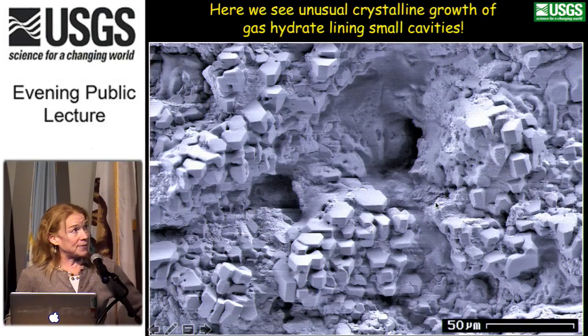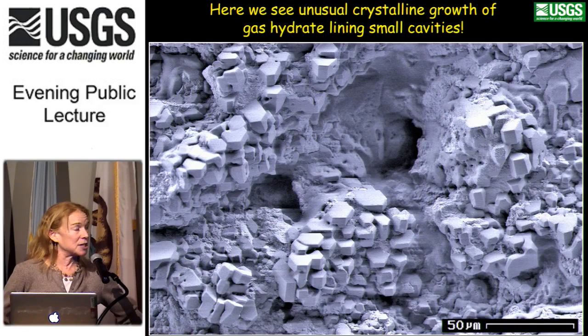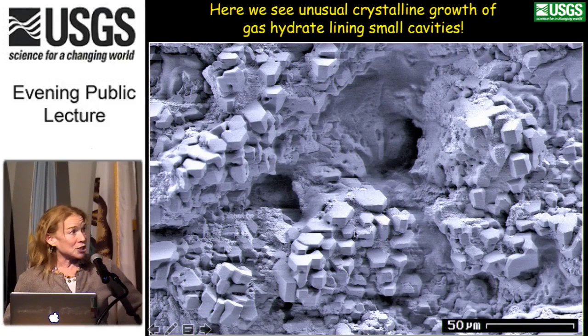This sample was very surprising in that it also had these small cavities that were just lined with beautiful and very, very small crystals. I've never seen anything quite like this in the laboratory. But we found this many times in this particular core, as well as some of the other cores from this expedition. So let's go in a little more closely and look at these.